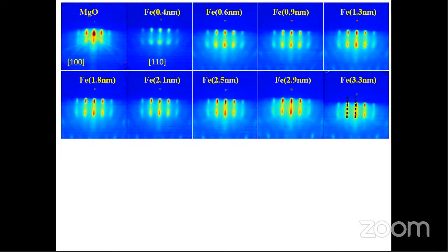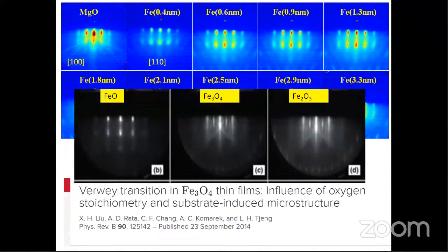as marked by the black line. If there were a streak or spot between two streaky patterns, then one could say there is a formation of oxide at the interface. But what we have found is, if FeO is formed at the interface during the growth of Fe, then one extra spot should be observed.